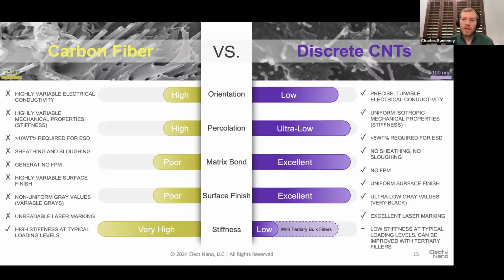But when it comes to consistency of electrical properties, if you're a computer chip sitting there in one of these little chip carriers and you've got an 8-micron diameter, millimeter-long carbon fiber embedded in a polymer matrix, the way that those carbon fibers align and orient during the injection molding process means that you have a highly conductive fiber and a very insulating matrix, arranged in a random or aligned pattern.